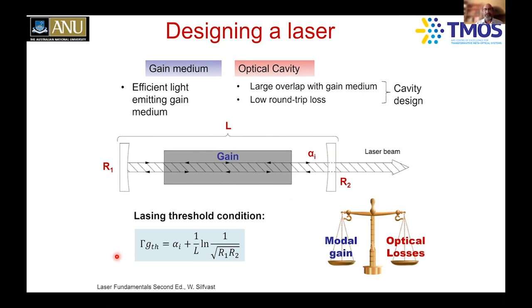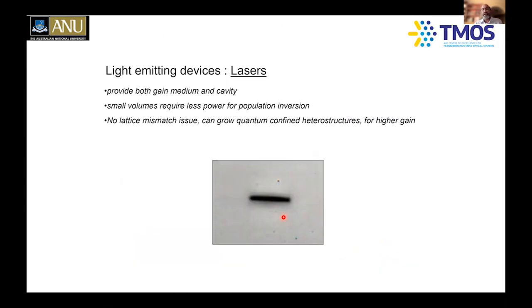Gain needs to be equal to the internal optical losses and mirror losses, and only then does lasing start taking place. So if you take a nanowire and excite it with a laser pulse, the nanowire acts like a waveguide because of its high refractive index of 3.4. Light starts propagating along the length of the nanowire.